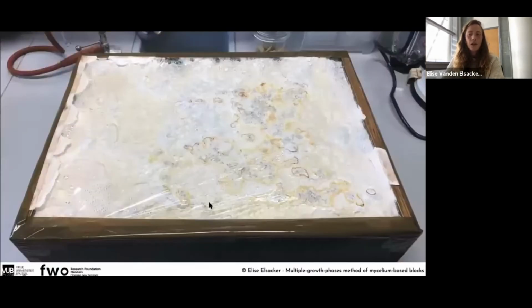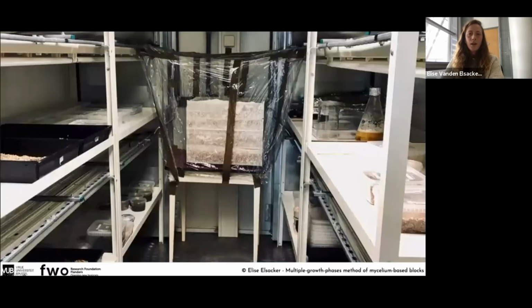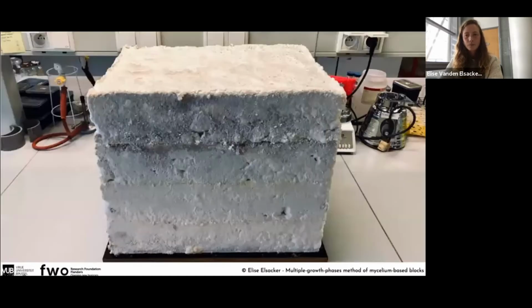The conditions were a regulated temperature of 26 degrees. After 3 days, the substrate had taken the shape of the molds. The reason why it's only 3 days here is because it had already pre-grown in the bags in advance. This was enough to remove the samples from the molds. Then the different layers were stacked on top of each other and incubated again for another 4 days. During this third growth phase, the different layers grew into each other.